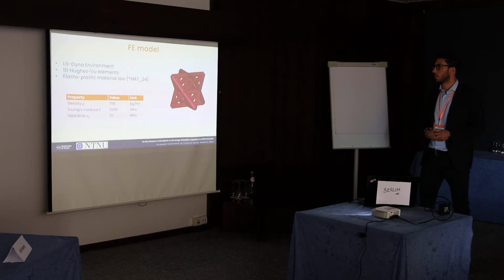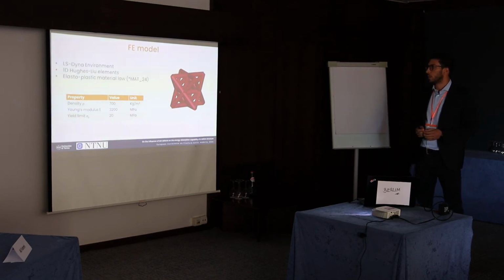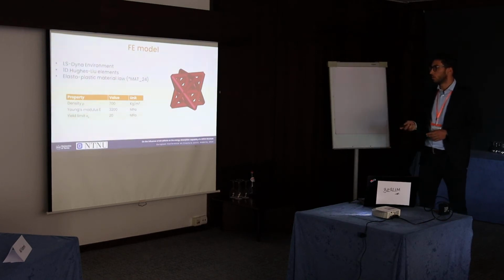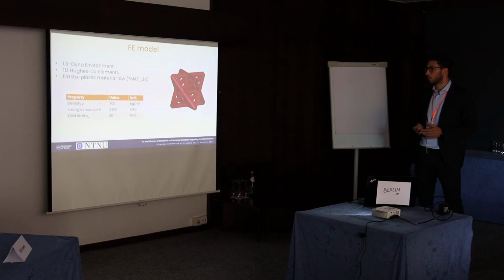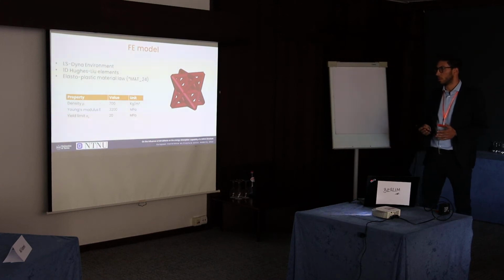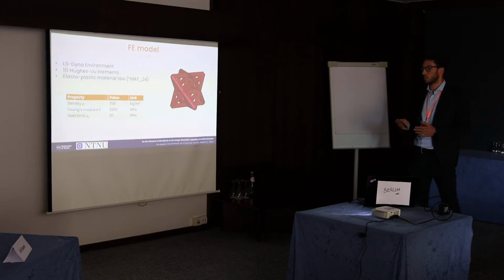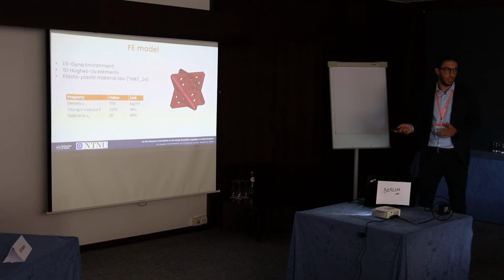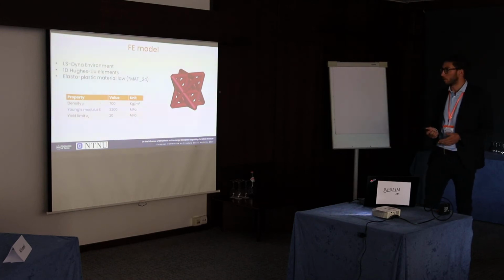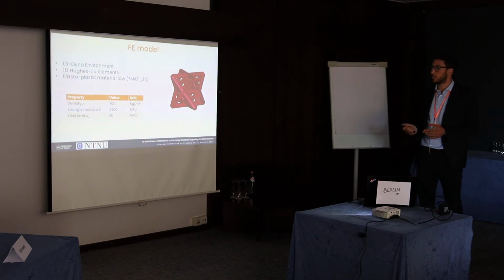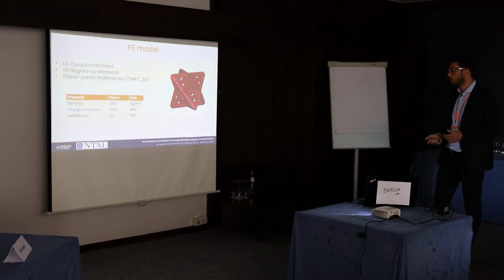And from the material point of view, we selected an elastoplastic material law, that is the material 24 in the code. Here I reported the material properties: density, Young's modulus, and yield limit. And for the plastic field, we conducted some tensile tests on specimens realized with the same material and with the same process parameters. So from that we extracted the plastic field, the stress strain curve in the plastic field.